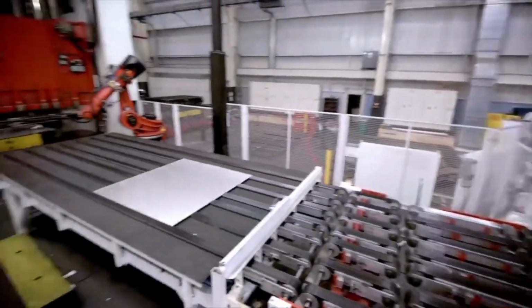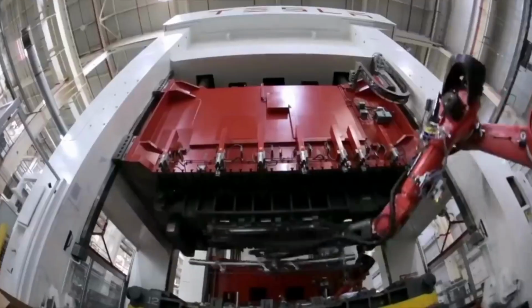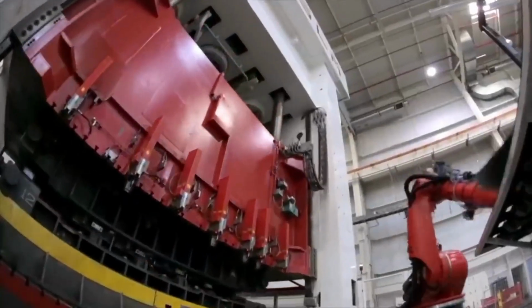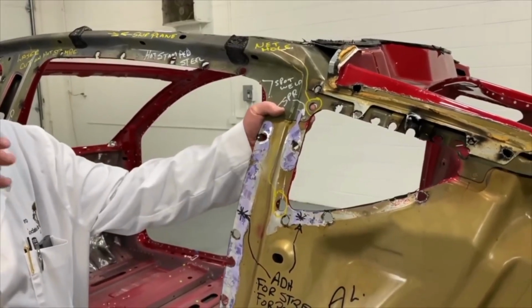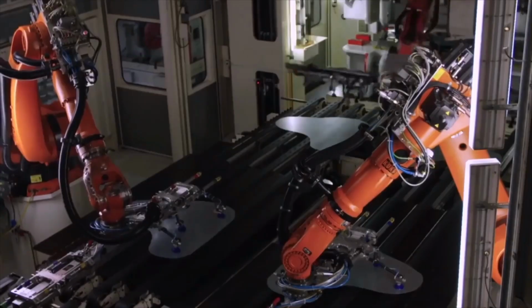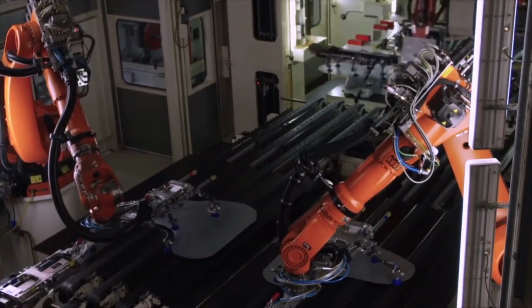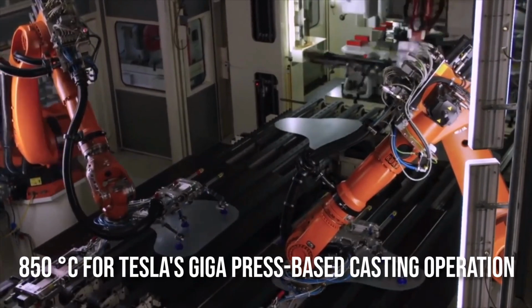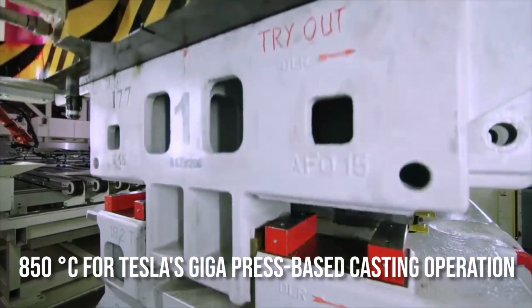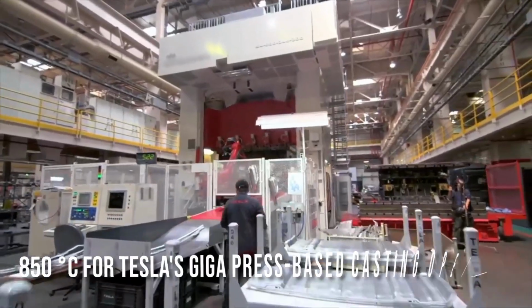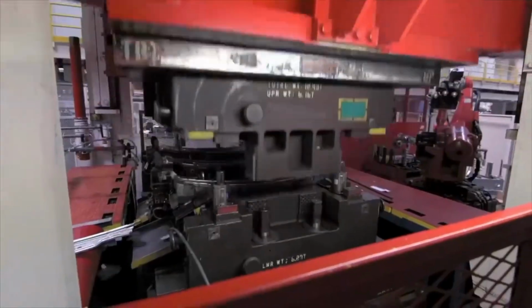Each new casting is trimmed to size, measured, and flaw checked before being sent to another machine to be fully polished and finished. Ingots and offcuts of aluminum are melted until liquid in a natural gas-powered melting oven at 850 degrees Celsius for Tesla's GigaPress-based casting operation. Aluminum oxide slag is mechanically removed from the surface.